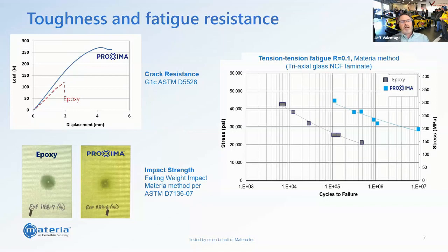So you can see here in these testing that we did with customers looking at toughness, the crack resistance is significantly higher with the Proxima materials. Typically with our materials, you just see a yielding versus the epoxy that is used with this general epoxy. Typically you have a catastrophic type failure. Again, we typically yield. You can see on the bottom left with the impact strength.